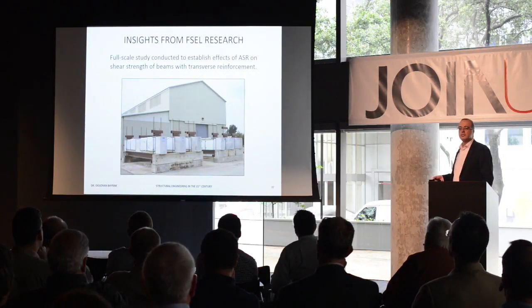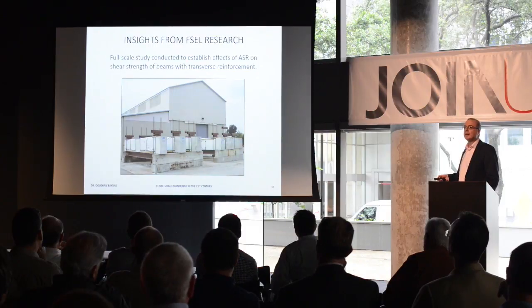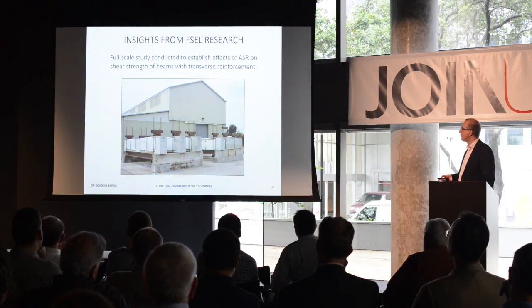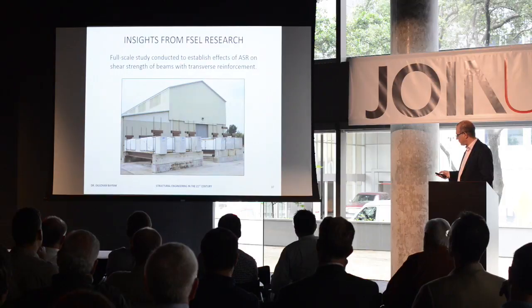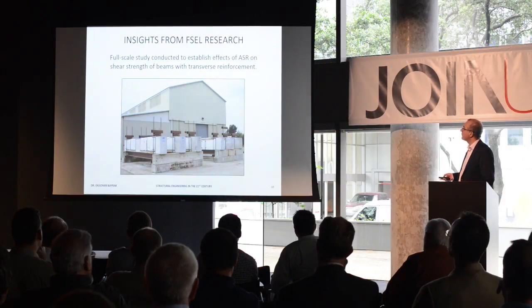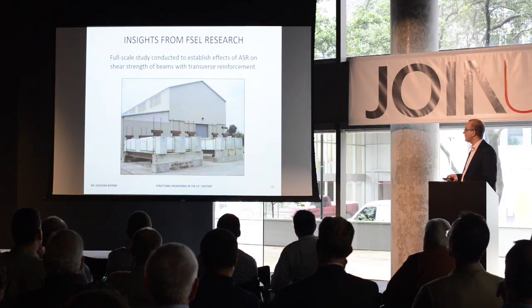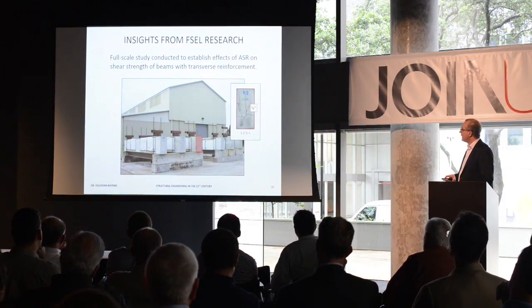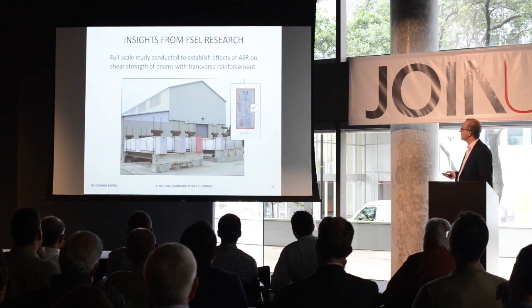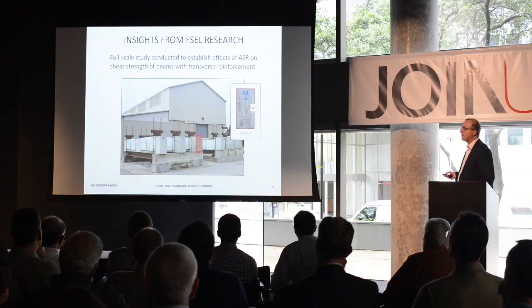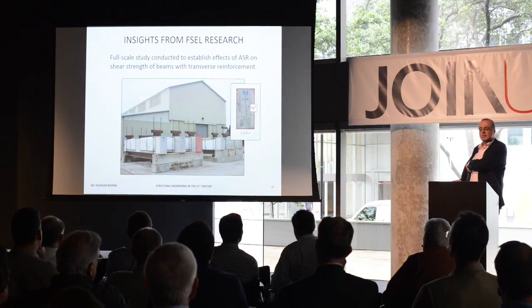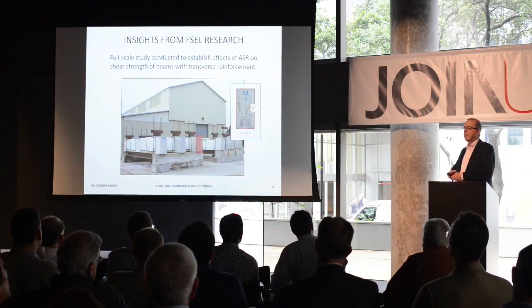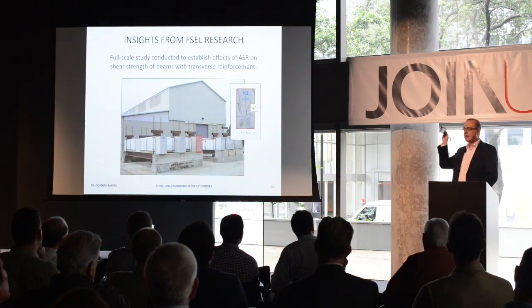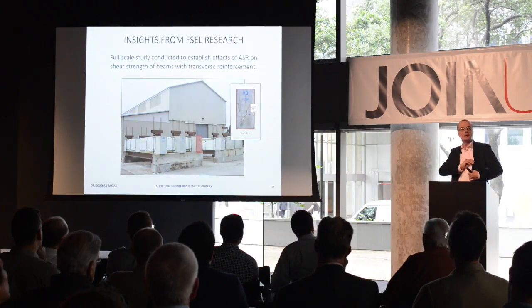I will share with you some of the results from a recent research project at Ferguson Lab. This is a research project that we have done for Texas Department of Transportation in an effort to establish the structural impact of ASR. Looking at the end of this beam R3 that was manufactured in 2007, so here's a crack width of about 5/8 of an inch, just for the purposes of scale. Basically what that implies is that you can have this iPhone and you can actually stick it into that crack.